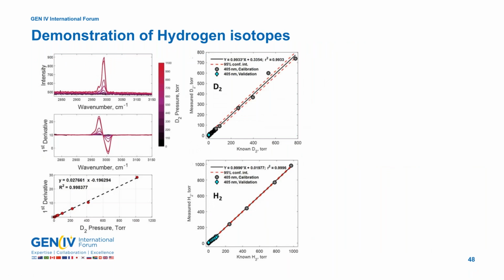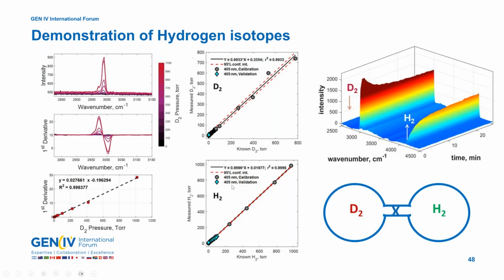The next slide shows a collection of some of the variable pressure measurements for deuterium. And again, doing the first derivative does a really good job at eliminating that baseline noise. And you see the baseline noise eliminated here. We use this data and others to go ahead and generate models for both deuterium. This is the measured deuterium pressure with our sensor versus the known deuterium. Same with hydrogen. We can use these models now to then predict concentrations in a variable deuterium hydrogen experiment. This shows an experiment where we start with our manifold line with two gases separated in two different chambers, hydrogen in one chamber, deuterium in another chamber.